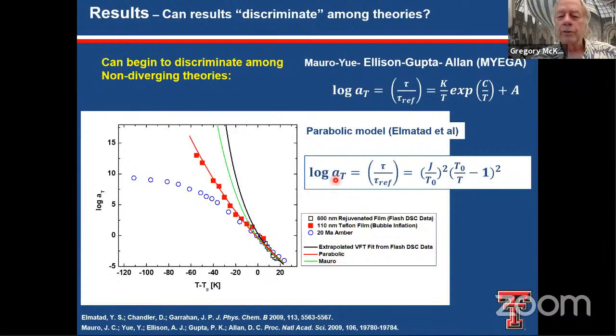We also compared it to two models at that time. We compared it to the MYEGA model, and we compared it to the parabolic model from Chandler. And the Chandler model is sort of a cheat because it's a fit. I think, Ken, you would agree it's a cheat. We had an arbitrary parameter, TX in here, that we, from there, make it an activated process, which is what they assume. But the MYEGA model, as we used it, even though it doesn't diverge, doesn't fit the data either.